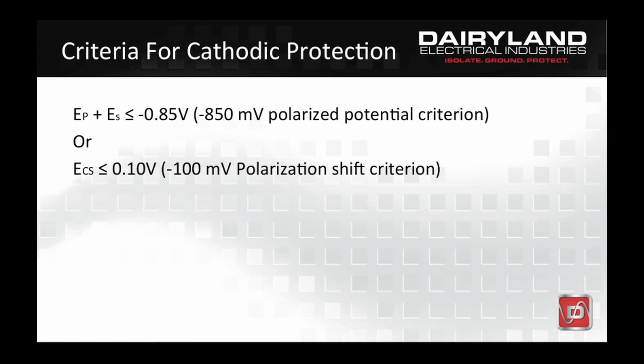Measuring minus 850 millivolts with respect to a reference electrode with the rectifier current on is not the same as the polarized potential criterion, because a potential measurement with the rectifier current on includes a voltage component commonly referred to as an IR drop error term. The 100 millivolt polarization shift criterion is most commonly used on pipelines in high resistivity soils or on poorly coated or bare structures where it is difficult or impossible to achieve the minus 850 millivolt polarized potential criterion.